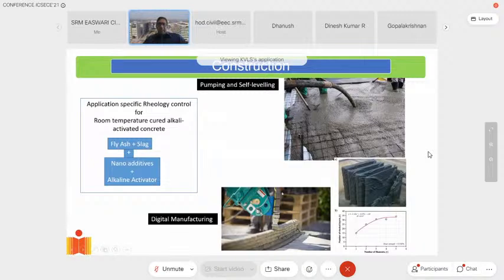So that of course again requires a tremendous amount of engineering of the material so that I can achieve this kind of flow that I need when I pressurize the material, and it should come to a rest and keep its shape. So that requires a lot of engineering of the material, playing around with the composition to deliver this fresh performance where it is able to flow under pressure, where it comes to rest and keeps its shape. And it allows me to stack layers one on top of the other. And by stacking multiple layers, I'm able to assemble the entire structure.